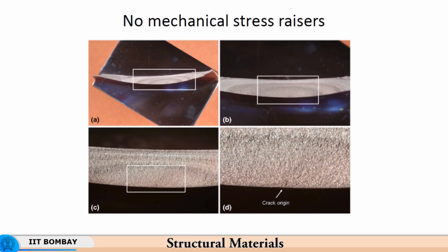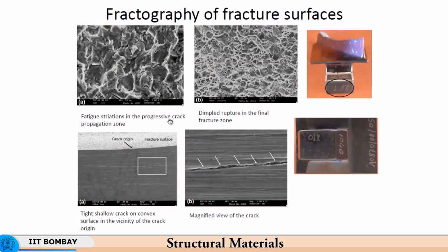So then it means that the reason should be metallurgical in nature, meaning there are certain soft spots which are being left behind. So the material has not been made hard enough, the material is not equally hard everywhere, due to which at the edges it got eaten away faster. Then there is a soft spot over here, due to which the crack originated, and finally failure took place.